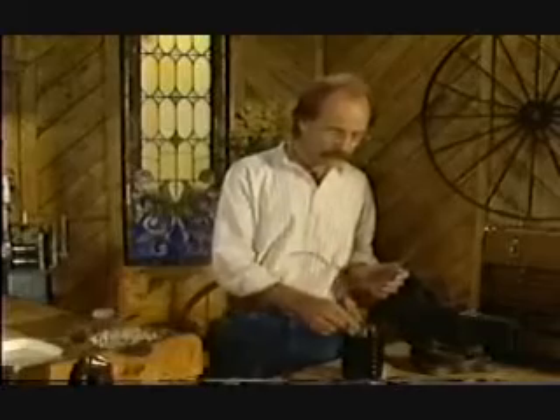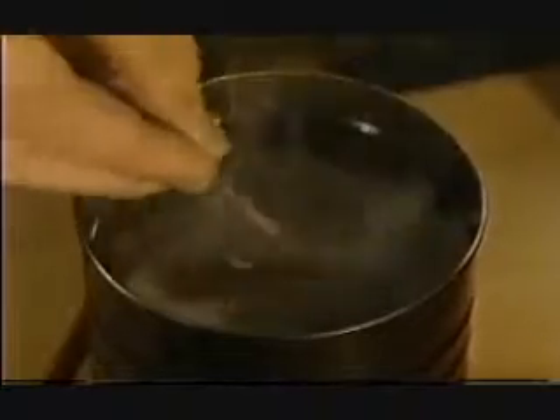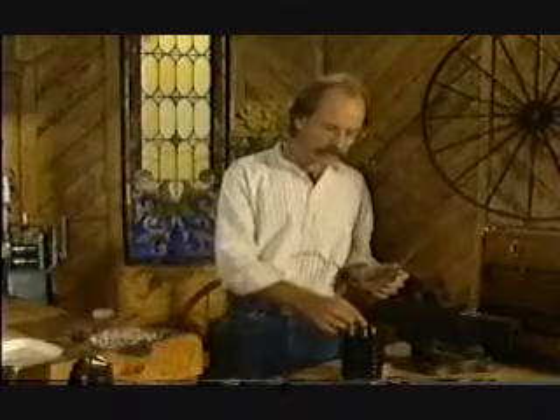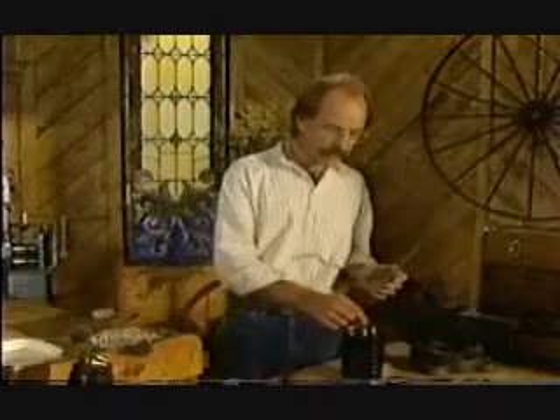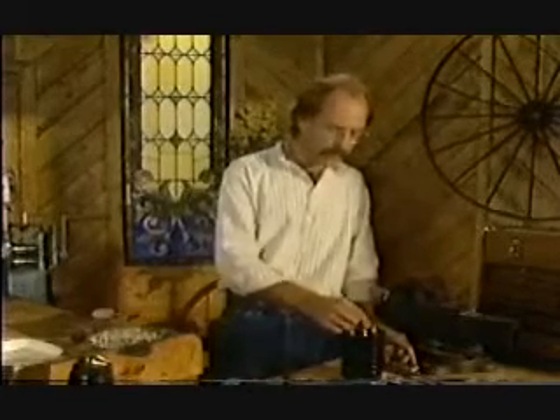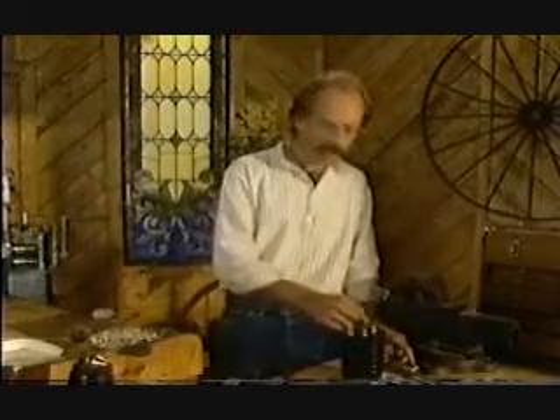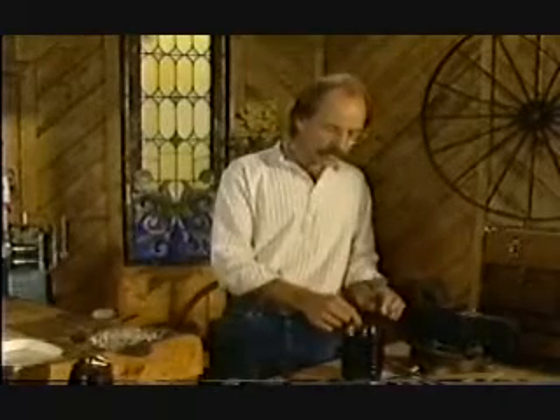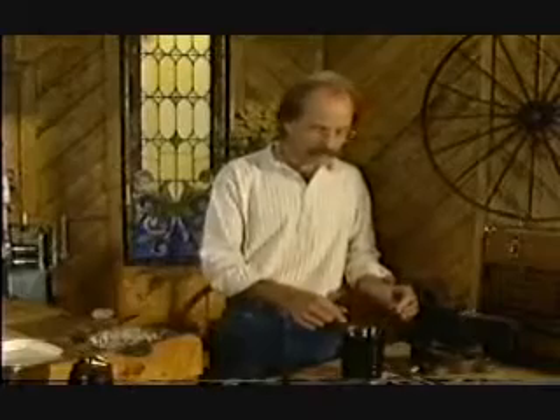And now I'm going to very quickly move over to the oil and stir with the tool. The stirring is important. If I plunge the tool in without stirring, it's immediately surrounded by an envelope of hot oil, and that defeats the purpose. By stirring, I'm constantly bringing it into contact with fresh, cool oil. I'll keep it there until it has cooled sufficiently to hold.